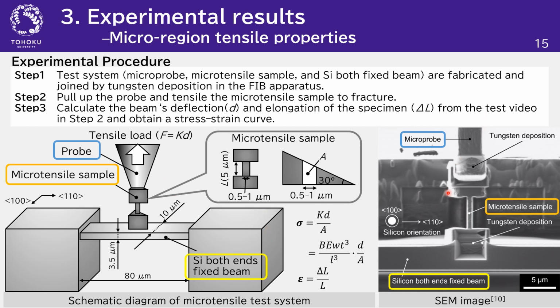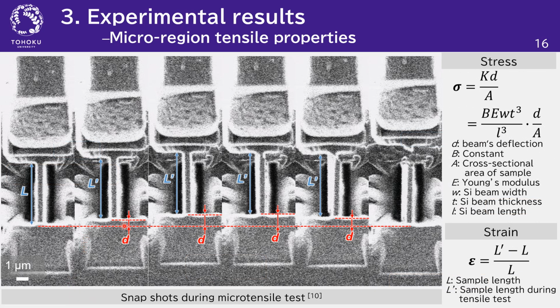Movies were taken during the test, and the amount of deflection of the beam and the elongation of the sample were measured from the snapshots of the movies to obtain the stress-strain curves. Here is an example of a snapshot obtained in the microtensile test movie. From the captured image, the length of the specimen and deflection of the beam during the tensile test are measured. Stress and strain can be obtained from these formulas.